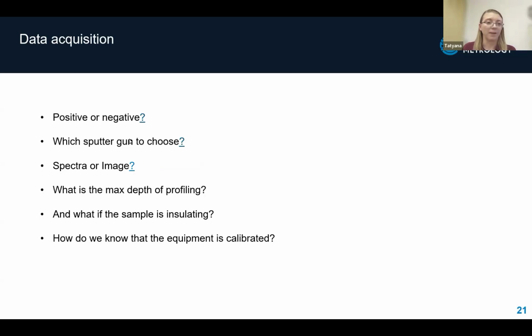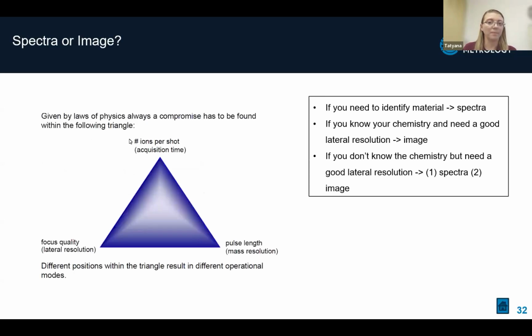Should we measure spectra or image? In physics, we often encounter situations where we need to balance multiple parameters, and this triangle perfectly illustrates one such trade-off. At the corners of the triangle, we have 3 parameters of ToF-SIMS. At the top, we have the number of ions per shot, which directly affects our acquisition time. On the bottom left, we have focus quality, which determines our lateral resolution. And on the bottom right, we have pulse length, which influences our mass resolution.